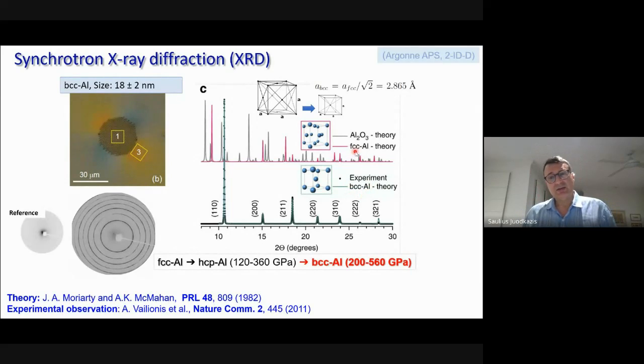What we have around is body-centered cubic aluminum, which is a much smaller lattice if you compare with the FCC. So this is a high pressure phase of aluminum. But let's remember, we started modification of sapphire, not aluminum. So what is happening is that we deposit energy, we create ionization of aluminum and oxygen, and then at the end we create the phases of high density aluminum. And the pressures you see here, which are required for those BCC aluminum structures, are huge. They were predicted in some theory papers years ago, but in this work we showed that we can have them in small volumes. They are nanocrystallites of around 20 nanometers in size.